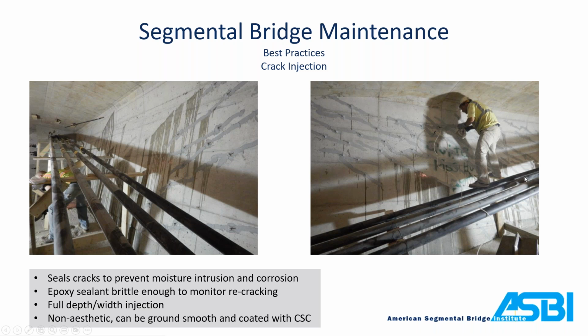And then you kind of work your way across. You cap this one, move your pump to here, so it starts oozing out of this one, and then cap, and then just keep working along the crack that way. It doesn't look pretty, but you can grind these down and do a concrete surface coating over it, and then you won't even know it's there. Nice thing about these epoxies, some people say, well, I can't monitor the crack if I do an epoxy injection. Most of these systems are just as brittle as concrete. So if your crack is propagating, these epoxies are going to crack, and you can still determine if the crack is moving or working while trying to seal it.